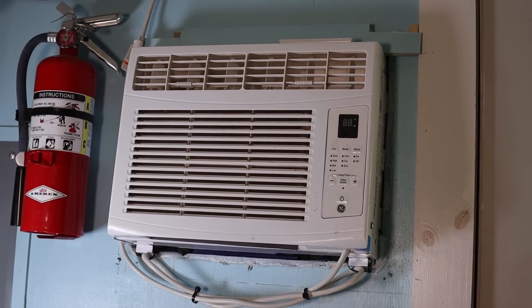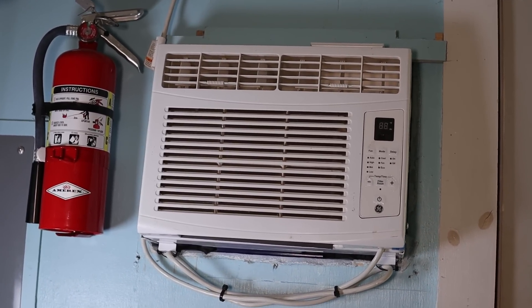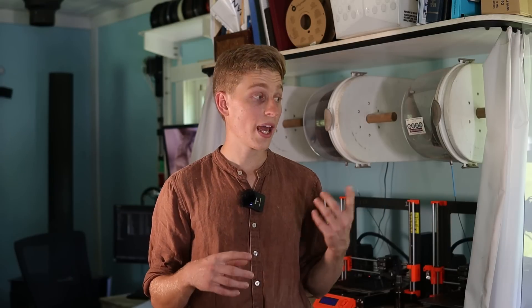To give some relative numbers: assuming a relative humidity of about 75% at 85°F — which is a quite humid environment I experience quite a bit here — your dew point is going to be around 75-76°F. Running this dryer at around 150°F internally, that'll result in a relative humidity inside the filament dryer of about 10%, which has been enough to keep the filament dry when I've been using it. However it's still pretty marginal. If that temperature were bumped up to 180°F — around 80°C — that number would jump almost in half, down to about 5-6% relative humidity, which is actually quite good.